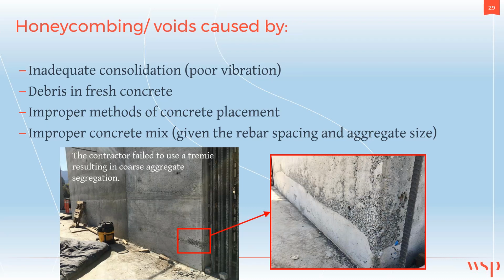This is an example of honeycombing caused by improper placement. You see that this is a heavily reinforced wall, and because of the reinforcement congestion, it was challenging to place the concrete, so they just dropped it.